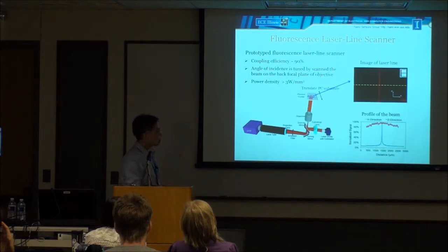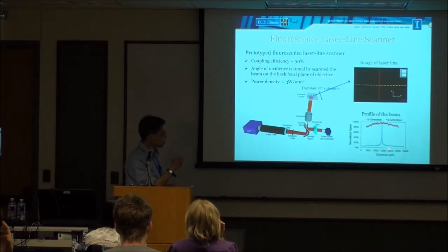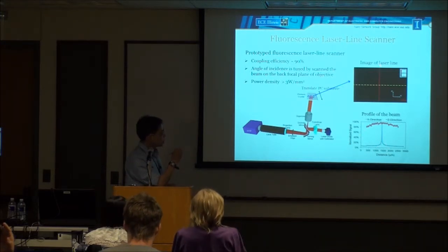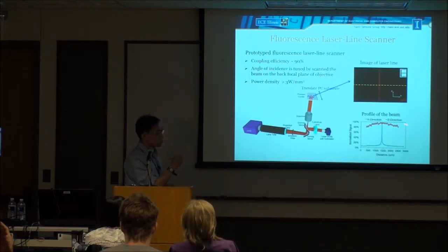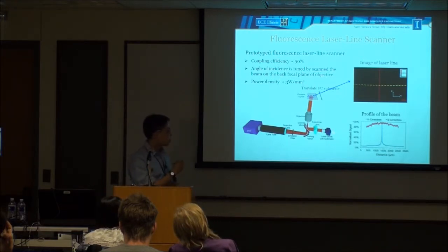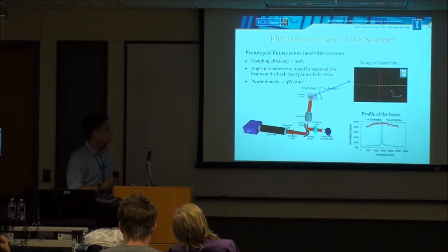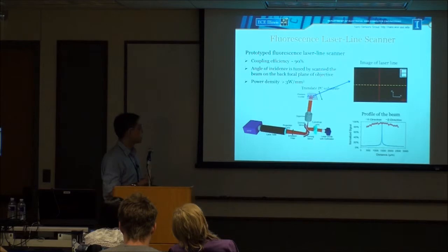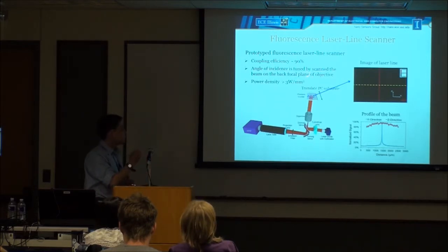This image shows how the line looks. The width of the line is 4 microns, so it can cover the full field of view of the objective. When we took a cross section showing the intensity of the line, you see it's pretty sharp. And along the line, it's fairly uniform, with variation less than 15%. In our software, we normalize this intensity variation and calculate the coupling efficiency. In this configuration, we can achieve 90% coupling between the incident light and the resonance mode. The angle of incidence can be tuned from 0 to 20 degrees, and the power density we achieve is 3 watts per square millimeter.